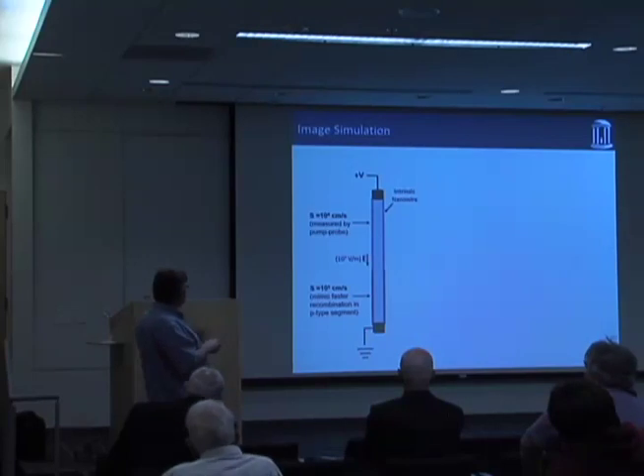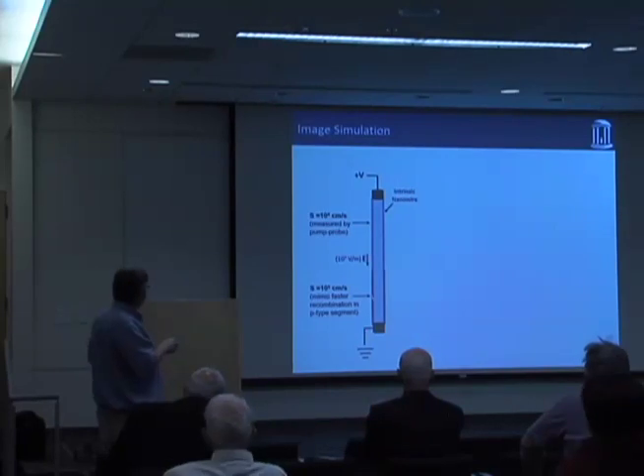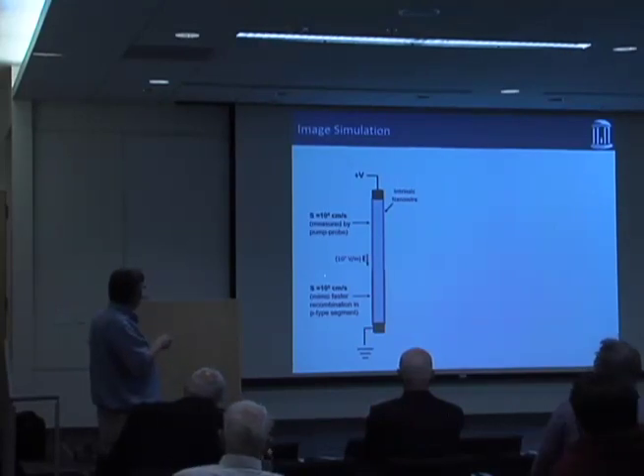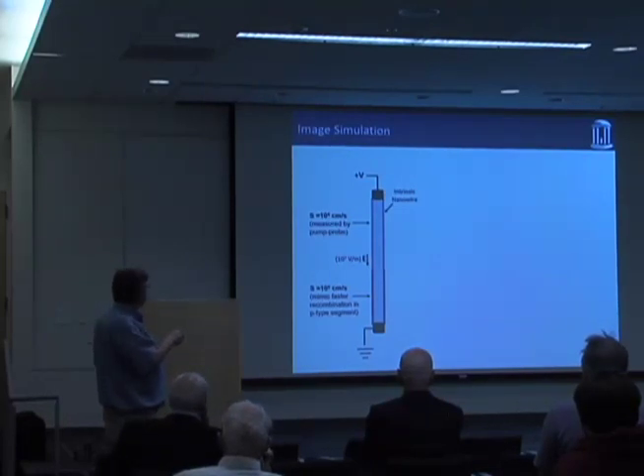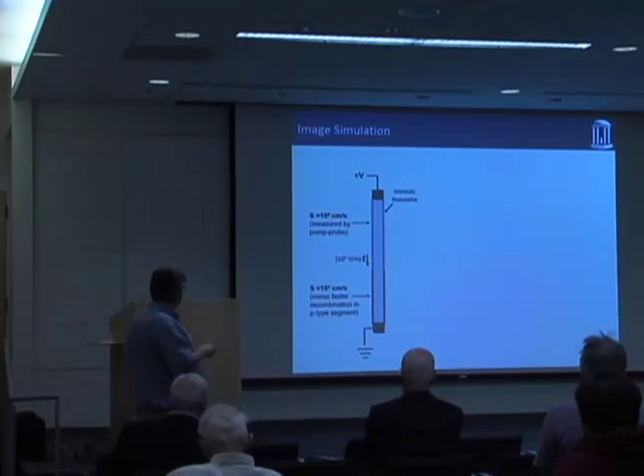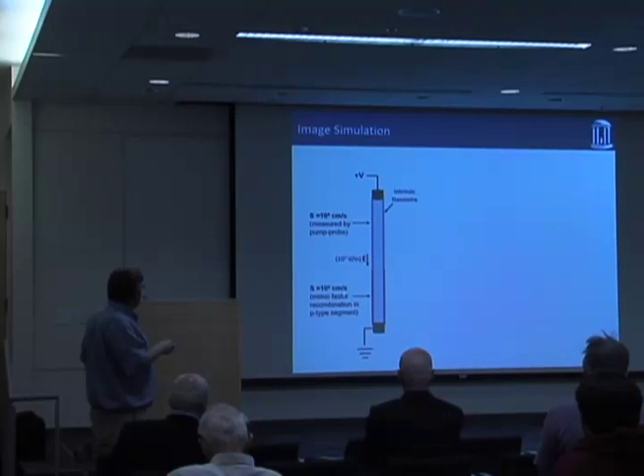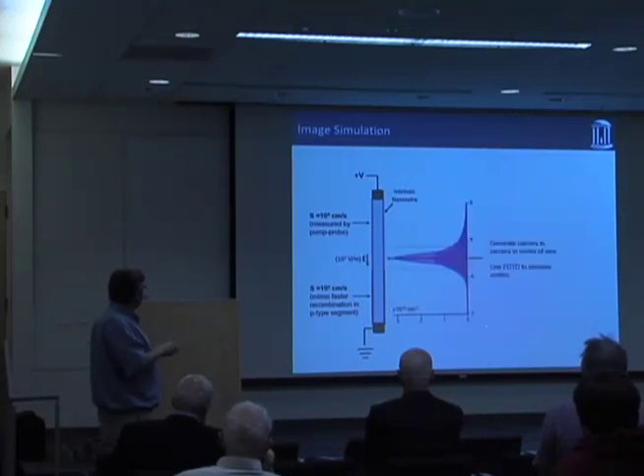And so we took that model that we had, essentially the same thing, but we made one small change to it, and that was we put the surface recombination velocity in the section that would correspond to where the p-type material was. We made that 10 times faster than it was on the rest of the wire, because in computers you can do these sorts of things. And the idea was that this was going to account for the faster electron-hole recombination in that segment of the wire. And then we run the simulations, and okay, here are